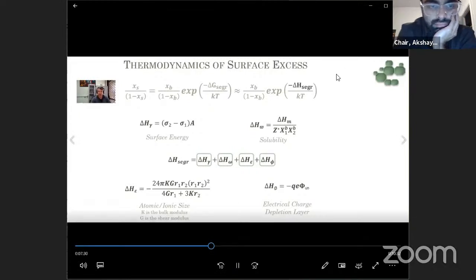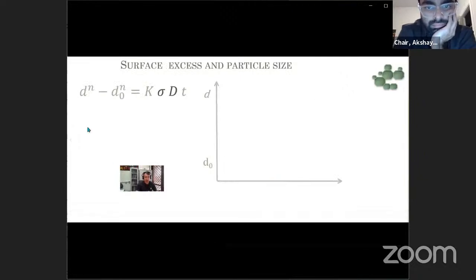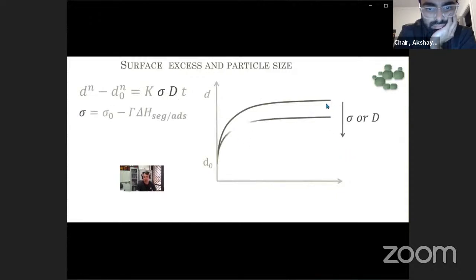One of the main consequences of surface excess is the stabilization of particle size. When you take this law of particle growth, the particle growth for time t depends on the surface energy and diffusion. And we have some kind of curve like that, and the n here is 2 or 3. When you decrease the surface energy or the diffusion, we have a decrease in the final particle size here. And we see this because when you have a surface excess, we have a decrease of surface energy and then the stabilization of particle size. And then a direct consequence is the increase of specific surface area for a long time of calcination.